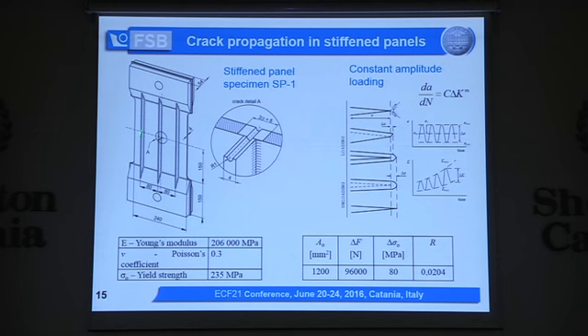And we are now back to our specimen. So we consider this one with a single crack, with a central crack, and this is intact. This is intact, and here is crack. The cracks look like this. And in 500,000 cycles it was broken.